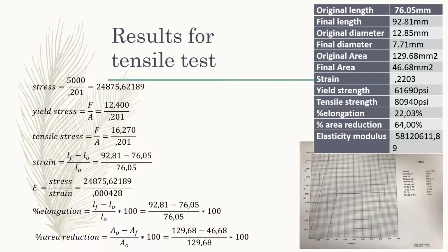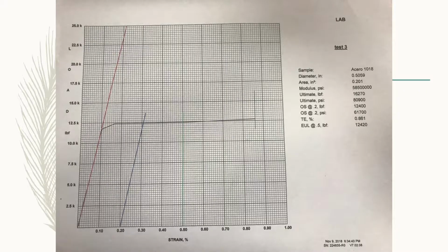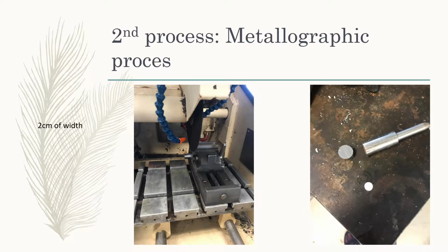it. We get the yield stress, tensile stress, strain, modulus of elasticity, and the percentage of elongation and area. We can see that the percentage of elongation was 22.03% and the percentage of area reduction was 64%. We get a yield strength of 61,690 psi and a tensile strength of 80,940 psi. These were the results sheet that the machine gave us.